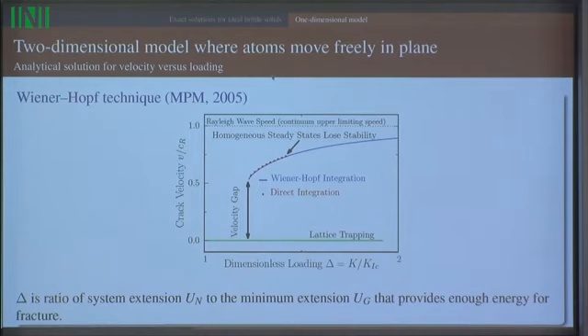So can I just get that clear? So you're checking the local bonds, and then you're getting this criterion that the bonds break at some angle as well as along the crack. Precisely. And the reason you can do it is because the nonlinearity is so sharp. So the law of interaction between the atoms is perfectly linear to the point of breakage by assumption. So you just assume that and look for the point where the assumption is no longer self-consistent, and that's the point where the instability would set in.